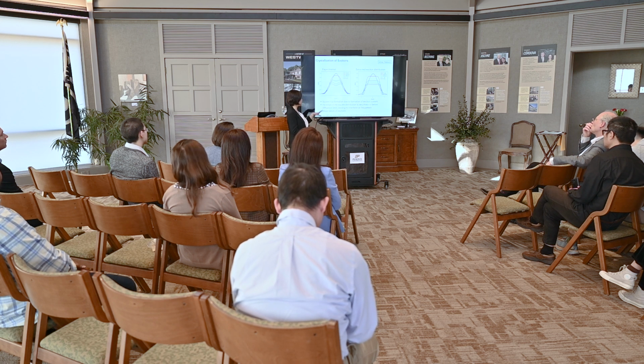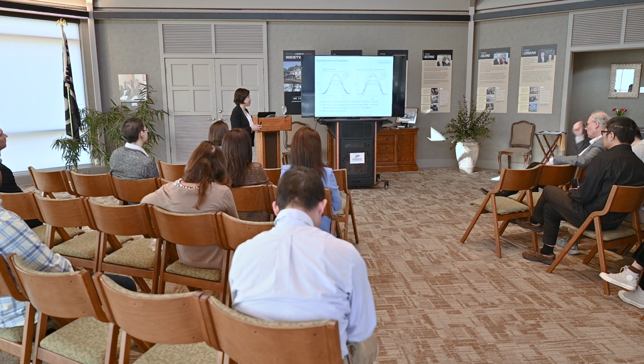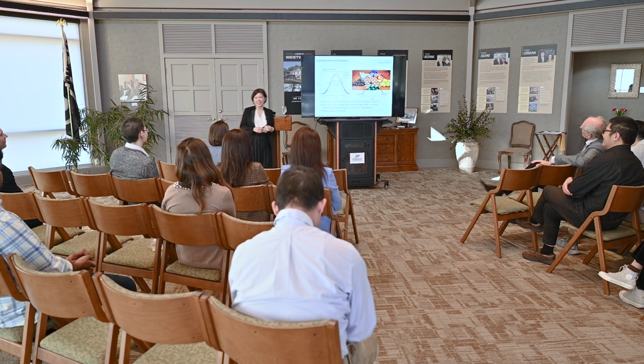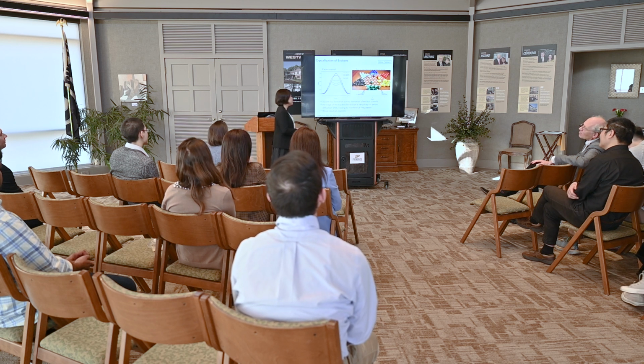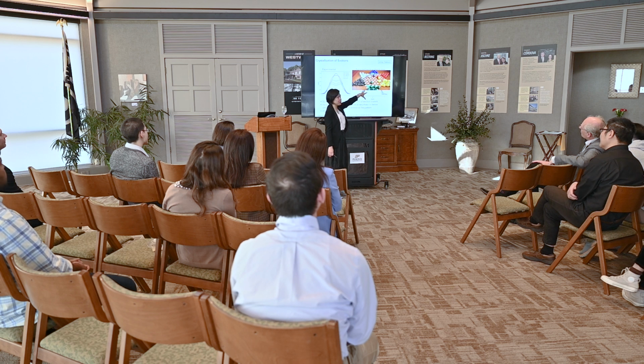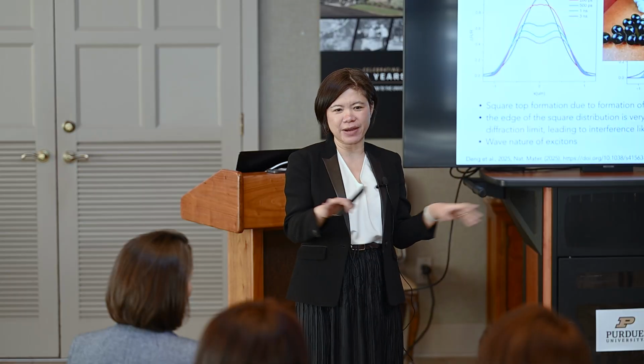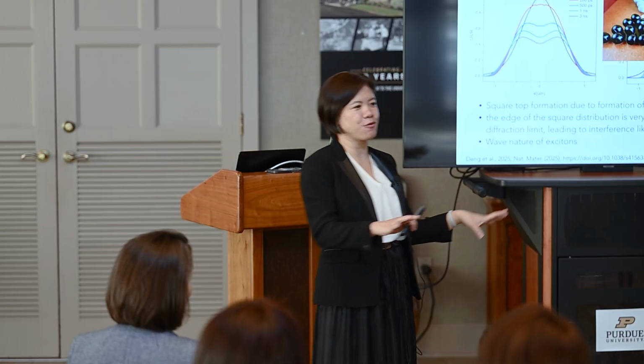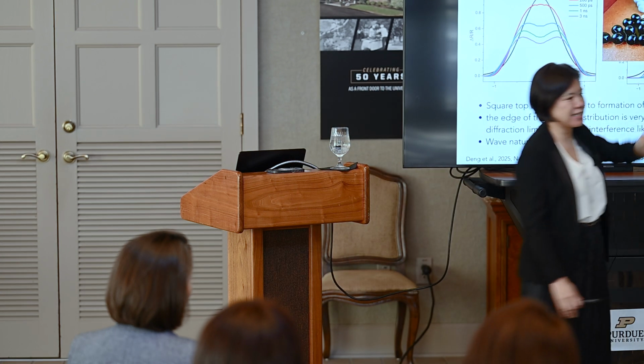And what happens there? If I take a cross-section of that image, this is what I see. Initially, it looks like a Gaussian because my laser beam is a Gaussian. But at later time, it actually becomes like a square. And the reason it becomes a square is because if you think about filling these excitons like a Chinese checkerboard, I don't know if you like to play, it's a very fun game if you have not played before. Chinese checkers have these holes on it, right? So the reason you form this square is that if you imagine a Chinese checkerboard, initially you pile all these marbles on top of each other, and then you let them spread out and find the most stable space, which is in the holes.